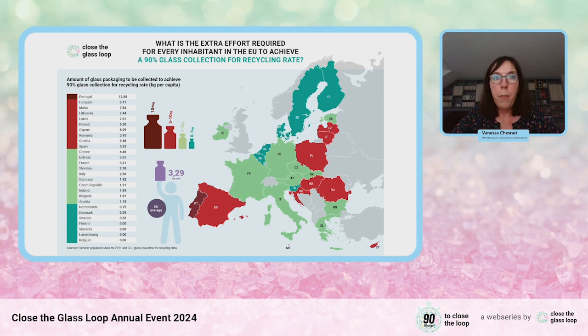So that's the collection map that we publish every year. And what we've tried to do is to look at collection from a different perspective. And here what you can see is the additional effort that is required for each citizen in the EU to achieve the 90% collection for recycling rate. So this map is based on 2021 figures, so we'll have to update it, but that's already a good indication. And so what you see is that across the EU, each citizen has to collect an additional 3 kilograms of glass to reach the 90% collection target.